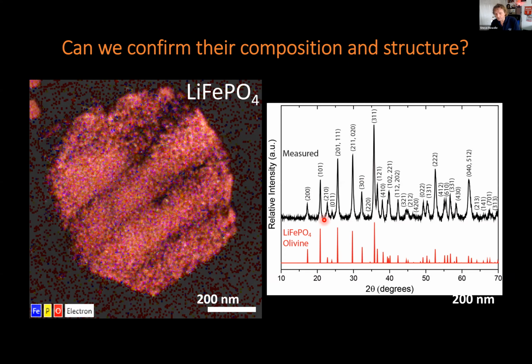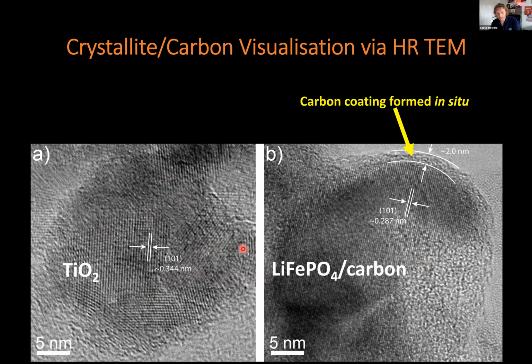So we've designed our polymer materials to enable us to template into some metal oxide materials. Looking very carefully at them, we get some really nice crystallographic structures of the metal oxides, and we can see very clearly in the X-ray and electron microscopy the phase boundaries of the crystal structures. We also found there's a little bit of carbon coating left behind that again should be useful for the technologies going forward.